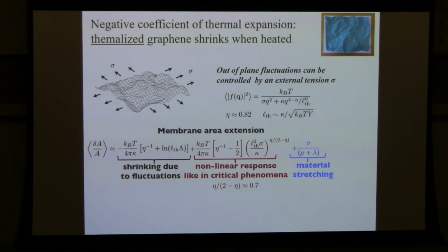And now let's imagine we do a little more sophisticated calculation. We can put a tension on the edges. We can look at the out-of-plane flexural phonons. This is like a phonon propagator. This exponent that controls the renormalized bending rigidity comes in. The important part of this fancy formula, which is just a formula for the shrinkage in the area, is this black term here. So you don't have to pay attention to this other stuff.